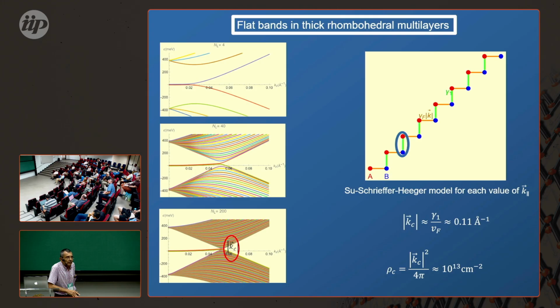The bands are always slightly dispersive. They are the flat bands you see there. They have a quadratic trend due to a parameter in the bands called gamma 4, which breaks electron-hole symmetry. So presumably you will always have this quarter metal phase at sufficiently low filling because you will occupy just the bottom of this quadratic band. Now, whether in addition you will get superconductivity is a different matter, and that's more complicated to answer. But definitely, I think you can go to many layers and still see magnetic or polarized behavior. But again, this is speculative. We haven't gone beyond 15 layers at this moment.